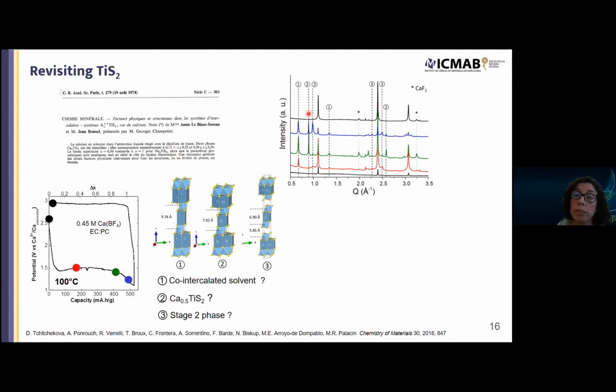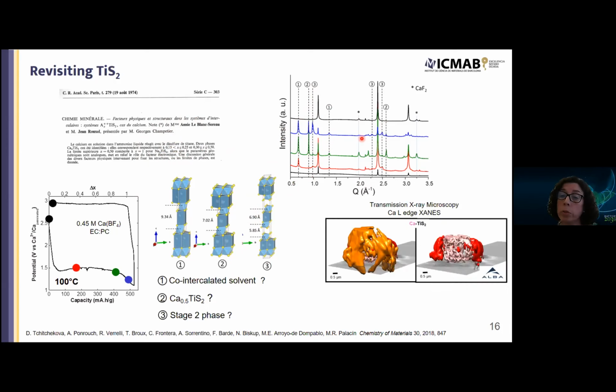As you can imagine, with these patterns, it was not possible to refine the calcium occupation in these crystal structures. So we turned to complementary characterization techniques to make sure that really these structural changes were related to intercalation of calcium, and we were able to do transmission X-ray microscopy at the calcium L-edge at the ALBA synchrotron. We were using different compounds as standards, and here is an image of what we get.